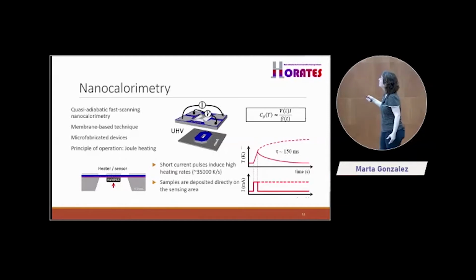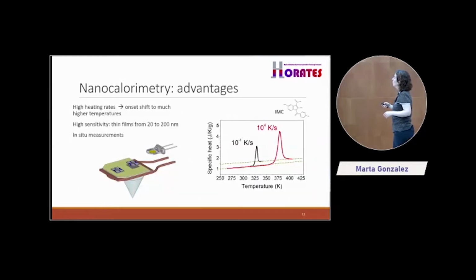So we are working in quasi-adiabatic conditions, it's written in the next slide. So all the heat that the sample is providing, we are registering it, we are getting it, okay? So it's really an extremely sensitive technique. So we can then get afterwards the specific heat from the voltage, the heating rate, and the intensity. I won't go into detail here.